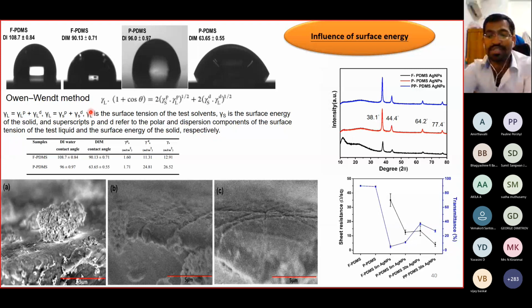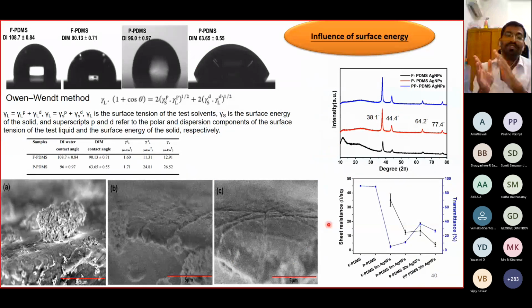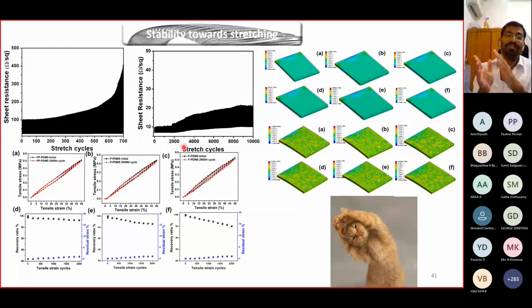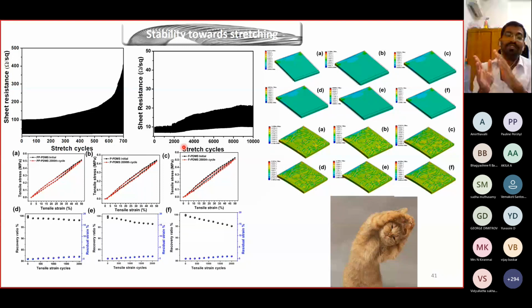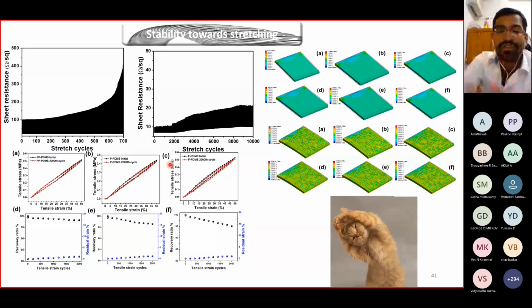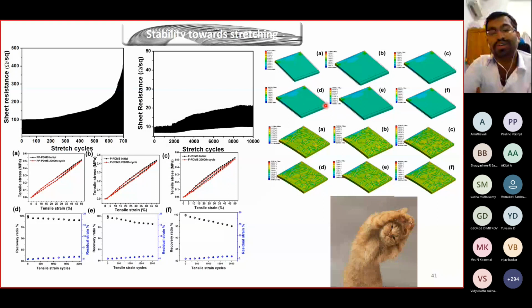So we optimize those things, and we also study the sheet resistance. If your sheet resistance is stable even upon stretching or flexing, then it can be a good electrode. That will be a very good substrate for building wearable electronics. So we are comparing the flat structures and the patterned ones. The flat structure is not that good, and you can see the resistance change getting higher and higher within 1,000 cycles. But for patterned PDMS, the stability of our sheet resistance is quite good even after 10,000 cycles. That is due to this kind of stress relaxation.